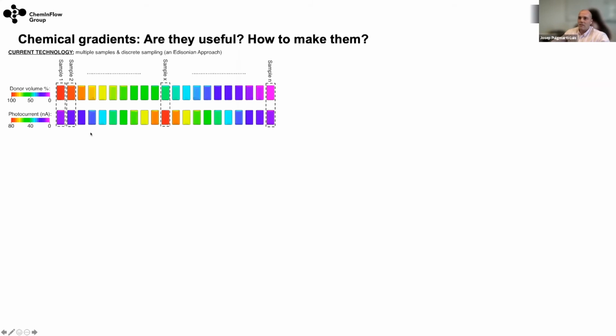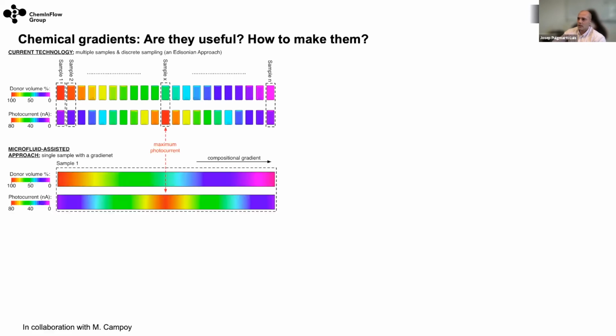The question I was trying to answer is with organic photovoltaics. As you know, in organic photovoltaics, you have a donor and an acceptor, and you always have to do multiple mixtures of the two to try to find the mixture that will give you the highest photocurrent. This is done via this Edisonian approach, right? You spend a lot of time doing different ratios in order to find the ratio with the highest efficiency. So the idea here was, if we are able to generate chemical gradients with one single sample, we will then be able to tell which ratio gives us the highest efficiency.